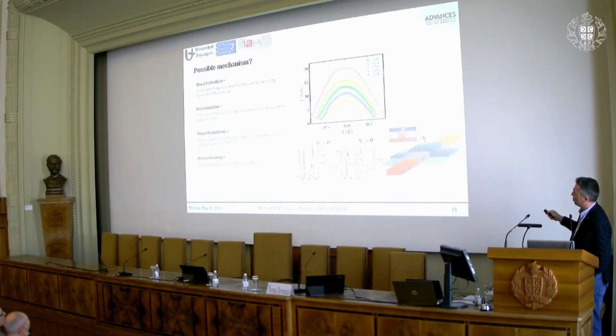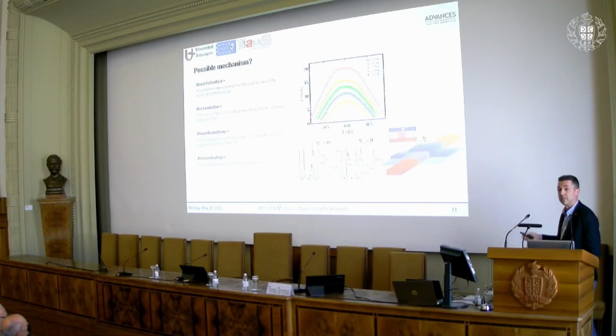And the asymmetry is due to whether we are injecting electrons from the gate to the superconductor or from the superconductor to the gate. In one case, we get phonon heating at the top of the oxide, in the other at the bottom, and that creates the asymmetry from the point of view of the superconductor.